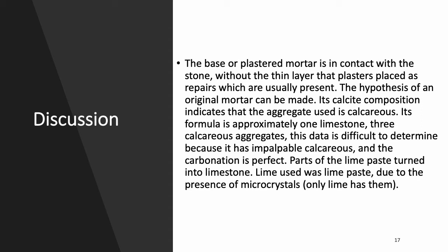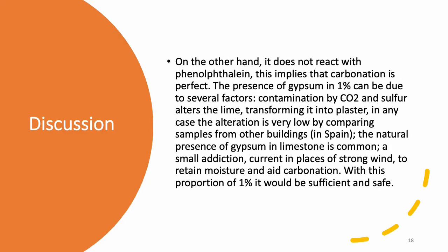This data is difficult to determine because it has impalpable calcareous, and the carbonation is perfect. Parts of the lime paste turned into limestone, lime used was lime paste, due to the presence of microcrystals. On the other hand, it does not react with phenolphthalein. This implies that carbonation is perfect.